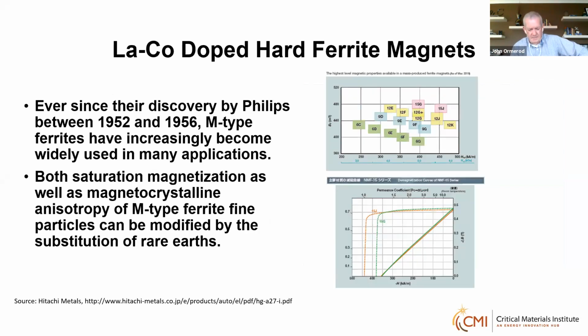And finally, let's have a word about a magnet material that, as I mentioned earlier, hard ferrite, is produced in the largest tonnage in the world. This is now benefiting from the doping of rare earth elements. What's been found is both saturation magnetization and magnetocrystalline anisotropy can be improved by the addition of lanthanum, and also cobalt helps. These magnets are now available with a 40% improvement in energy product over the conventional strontium hexaferrite magnets.